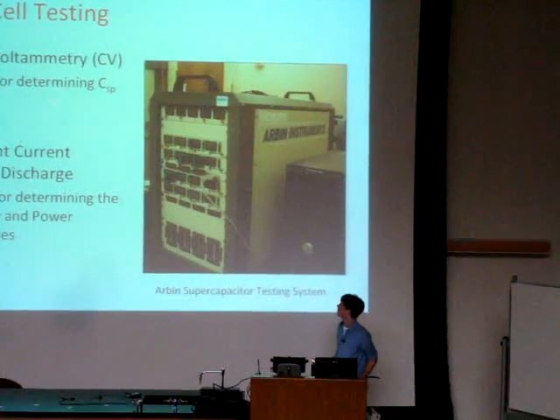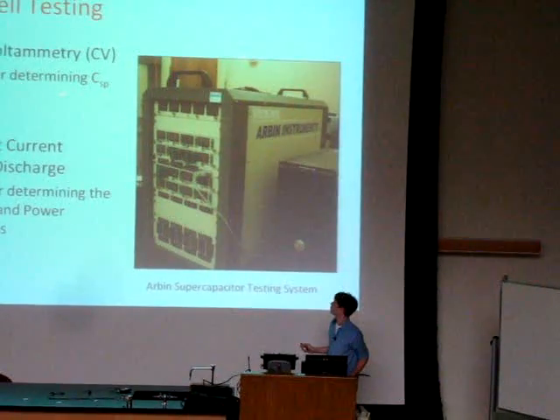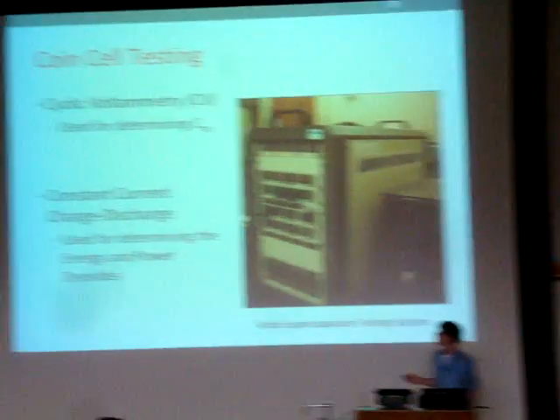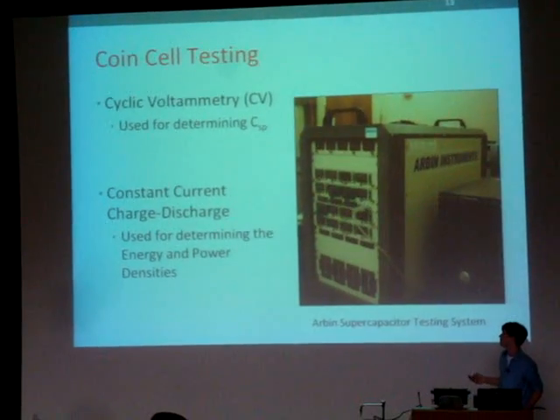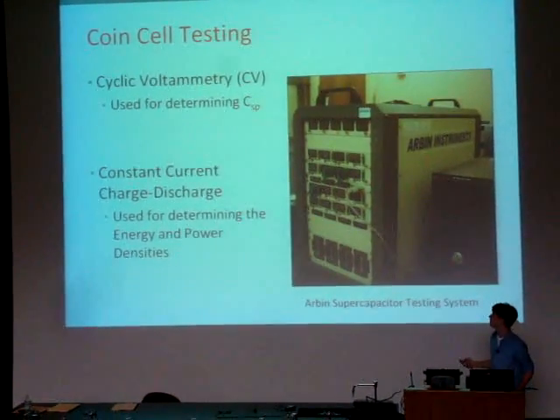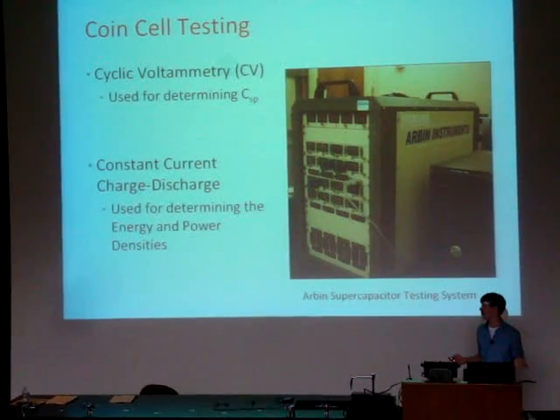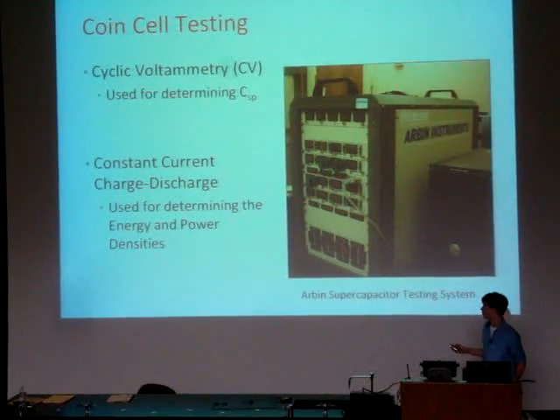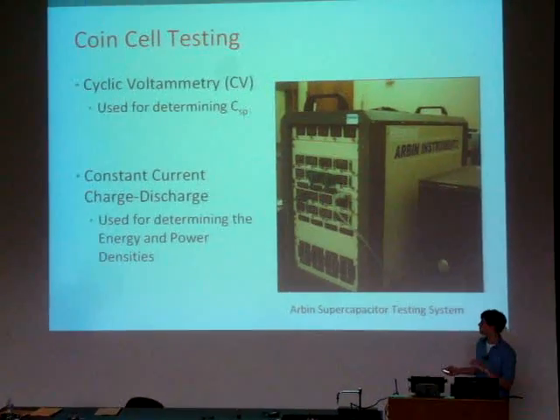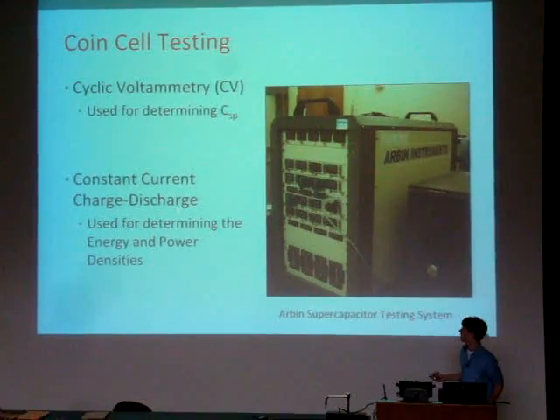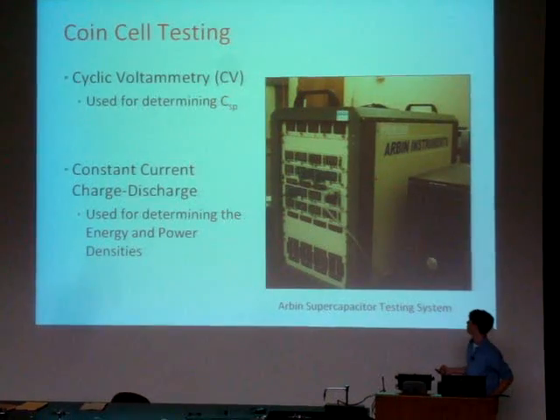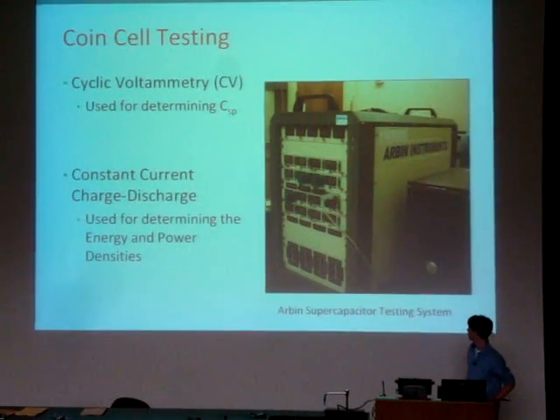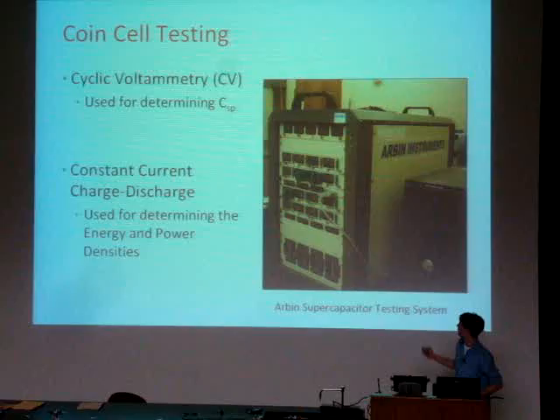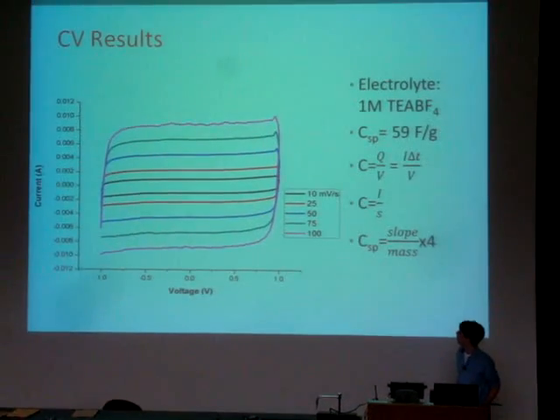Then we went on to testing the coin cell. We used 2 types, cyclic voltammetry, which is a voltage sweep, and that is used for determining the specific capacitance. We tested at different scan rates, 10, 25, 50, 100. And then we did constant current discharge, which ends up charging it from -1 volt to 1 volt, since that's its voltage window. And we ended up finding the discharge time to find the energy and power density. All of this was done using the Arbin supercapacitor testing system, as depicted there. So now on to the results.